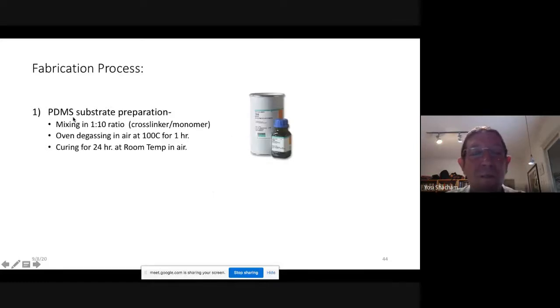So I'll go quickly. First we take the PDMS. PDMS is a polymer, an elastomer. It's not going to be a class in material science, but the way to make this polymer is you buy the cross-linker, you buy the monomer, you mix them together, wait 24 hours, and you have the polymer. So we can control the composition. For example, 1 to 10 is very much used. The reason I'm showing you this slide is that we can control the mechanical properties of the polymer, and this is going to be a big issue.